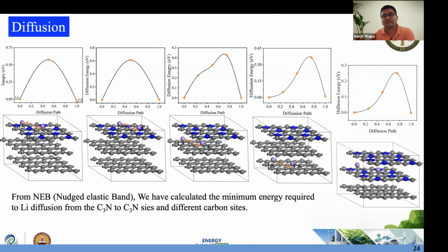So diffusion kinetics, again, we have done it, and we have shown that diffusion is changing from 0.5 to 0.3 in different layers of C3N or graphene.